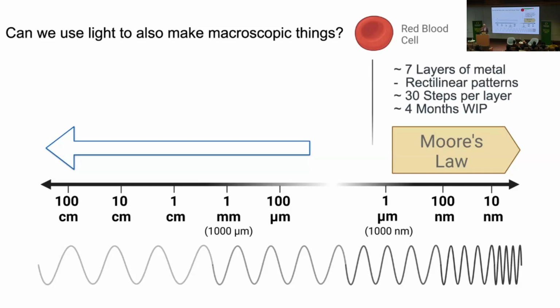Many, many, many steps per layer, as I just walked you through, to make a single layer. And then you have to do multiples of those layers to build up that structure, often 30 steps per layer to make that. And it's not uncommon for that single wafer to be in a factory for about 4 months, going through each step. 4 months in manufacturing something that's very, very thin.